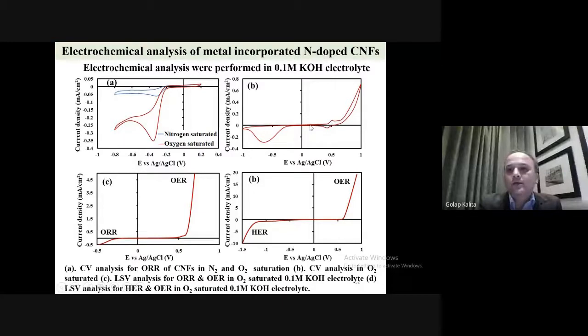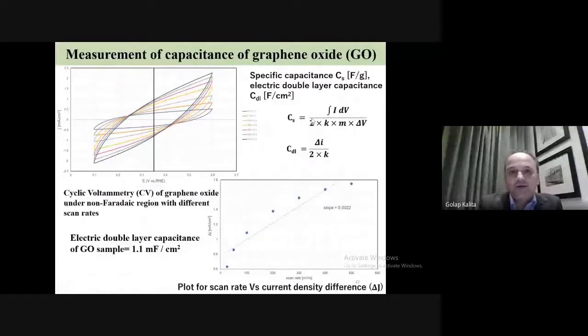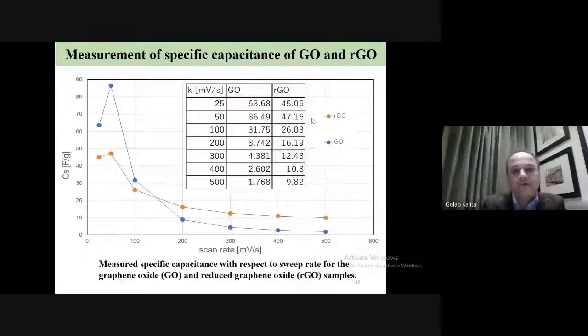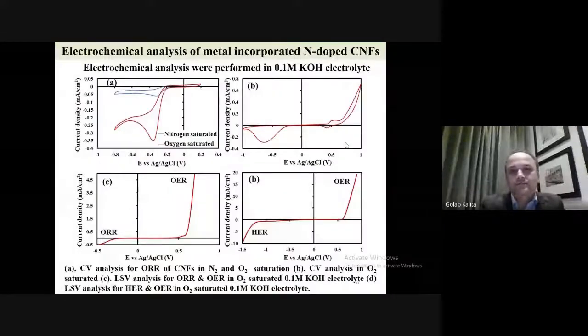Then there are 2 other peaks. If you have studied electrochemistry, this is the oxidation of the metal. We have nickel chromium, so you can see there is an oxidation of nickel here, and when you come back, this is a reduction. This is a Faradaic region where you have chemical activity, but when there is no chemical activity, this is the non-Faradaic region. Capacitance measurements are done in the non-Faradaic region of the material. So this is a Faradaic current, and this is a non-Faradaic region where we can measure the capacitance of the material. So this is a CV analysis.